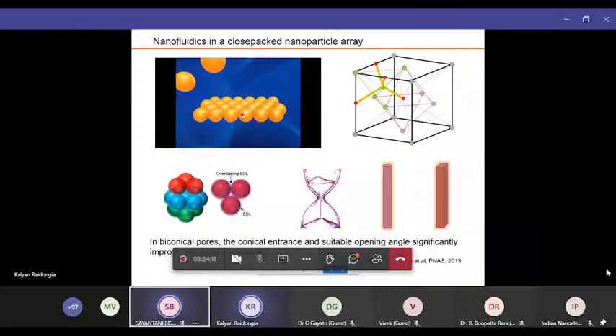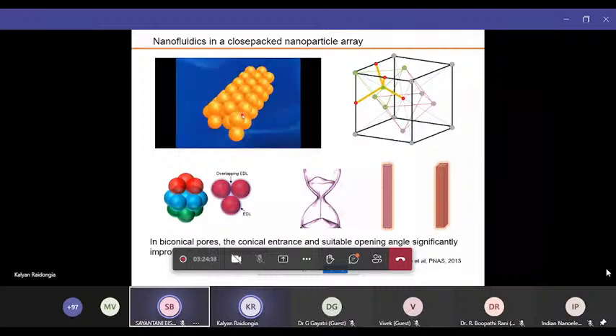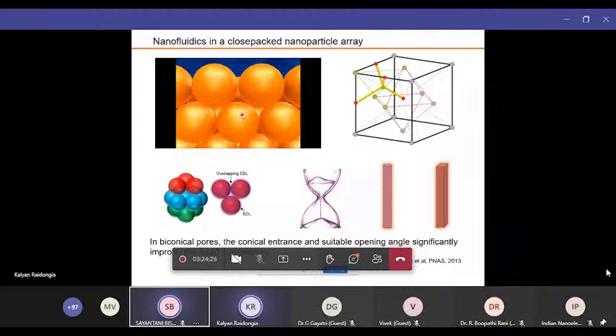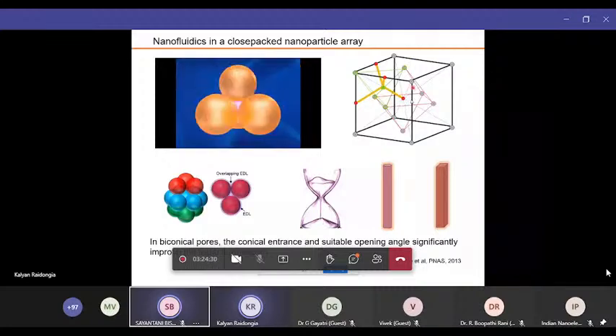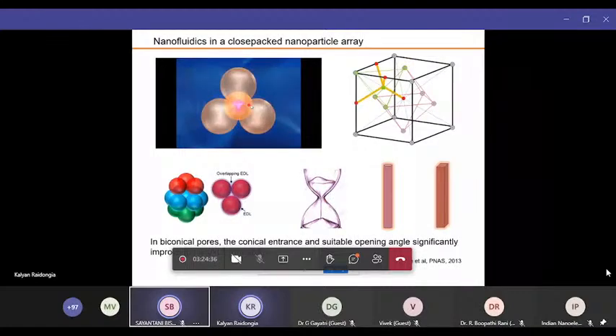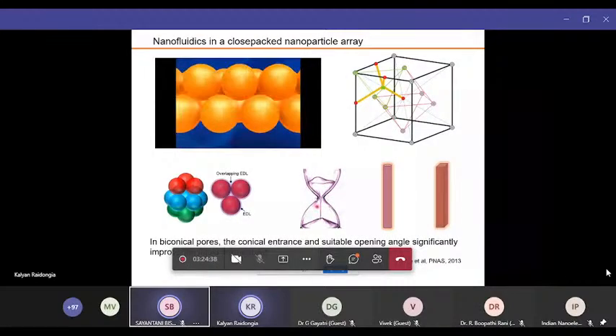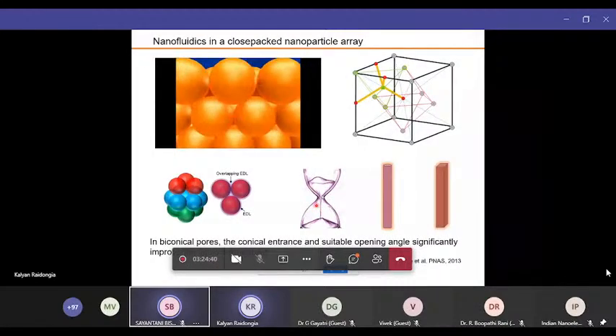So from our higher secondary knowledge itself, we know that when monodisperse spheres are allowed to settle one upon another, there are some vacancies between the spheres, some tetrahedral and octahedral vacancies, and these vacancies are not random. They are very well defined and connected to each other through well-defined channels. And if you can imagine this connection between the holes, these vacancies can be some biconical pores, like glass shaped pores.